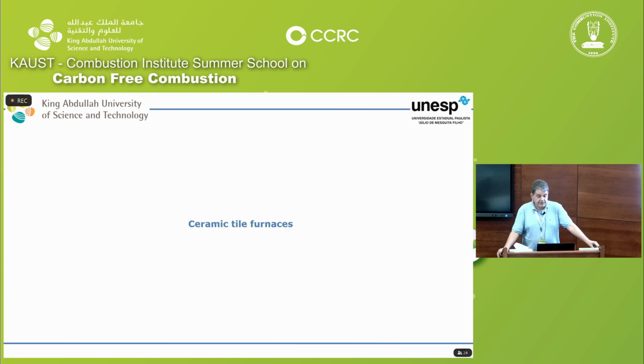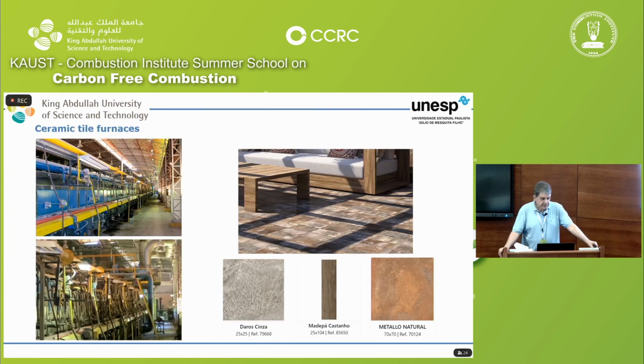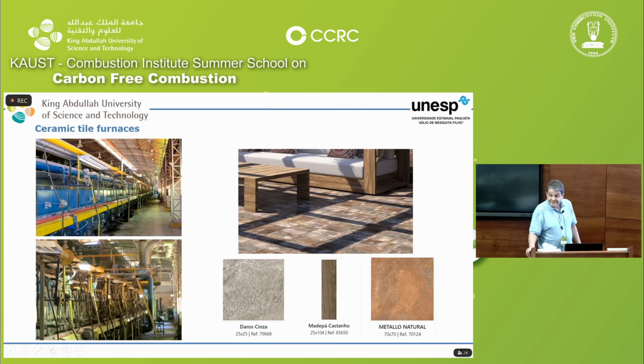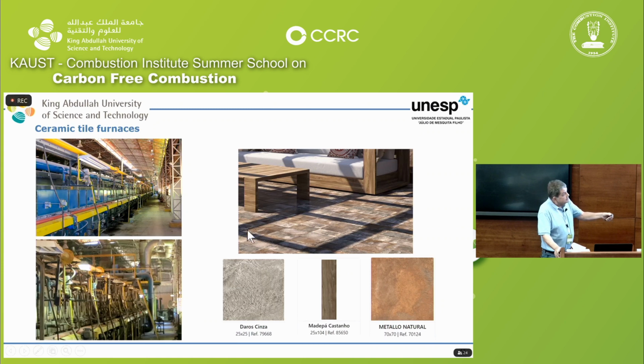Then ceramic tile furnaces. We also did some work with this kind of industry in Brazil. You see here is one in Porto Ferreira, which is in the interior of the state of São Paulo. This furnace is about 100 meters long. You see the ground is dirty. This air tubing here does not exist. And you see how many, the yellow is natural gas, the quantity of burners that you have. And they make these very nice tiles. Very nice ones.